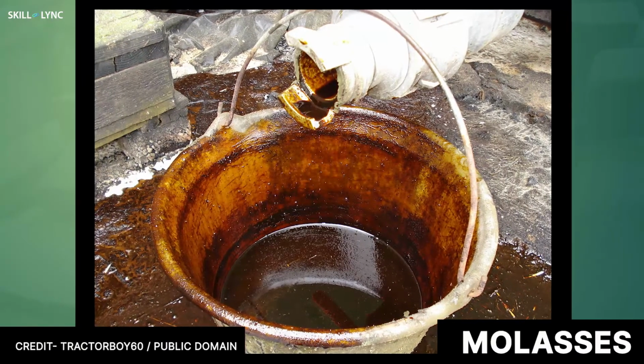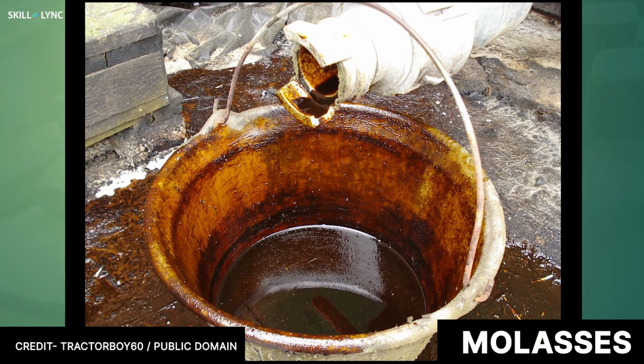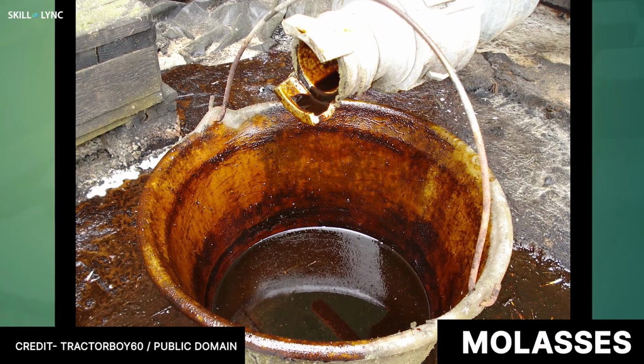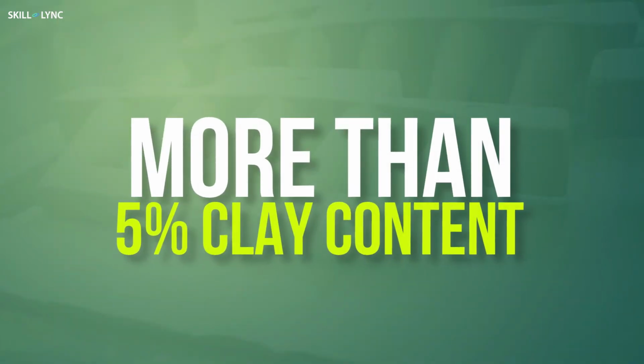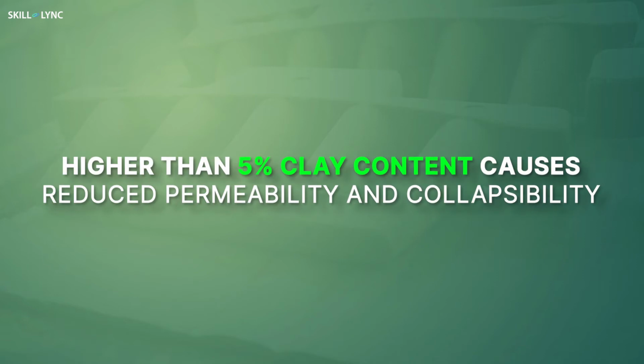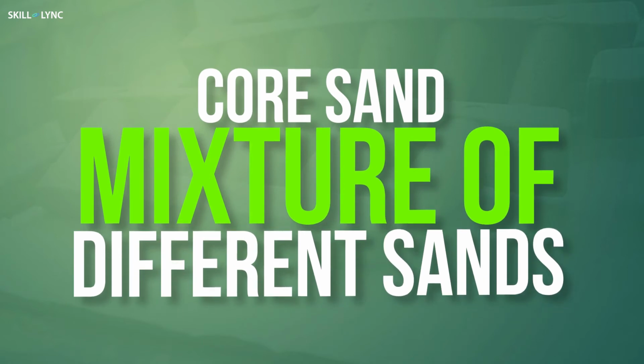Binders are used to bind sand particles together, and resins, molasses, etc. are some of its examples. The sand for core making must not have more than 5% clay content. Having higher clay content will reduce the core's permeability as well as collapsibility. The commonly used core sand is a mixture of several sand types such as oil sand, resin sand, etc. Let's discuss them in detail.